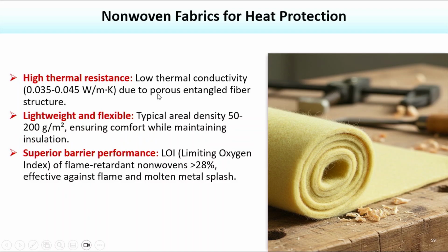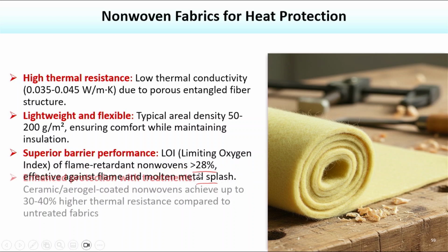Superior barrier performance. LOI of flame retardant non-woven is more than 28%, although that depends on the type of fibers used. Effective against flame and molten metal splash. So, non-woven can be used for molten metal splash protective clothing.